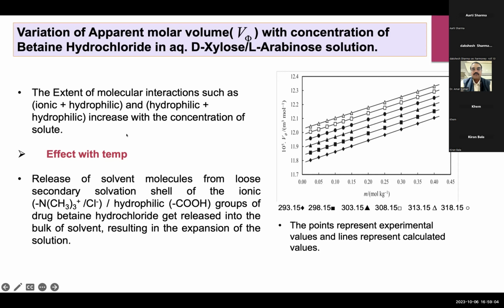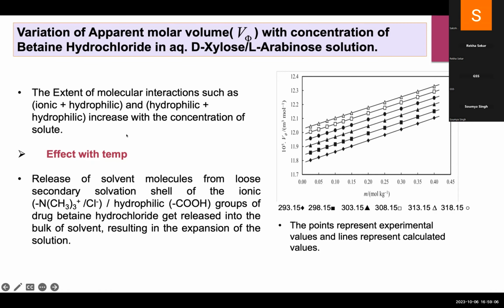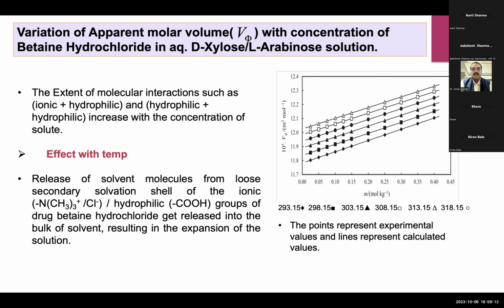This also shows that the ionic-hydrophilic interactions and hydrophilic interactions increase with the increase in the concentration of the solute. So the graphs at various temperatures, with respect to the concentrations, were also found to increase. This graph here depicts the values as the temperature rises.